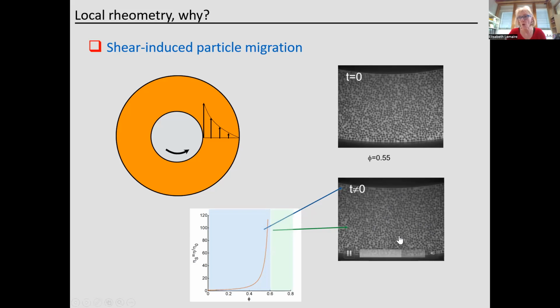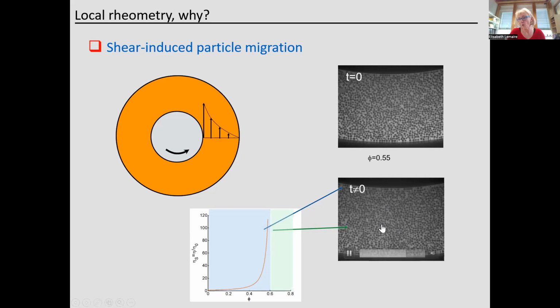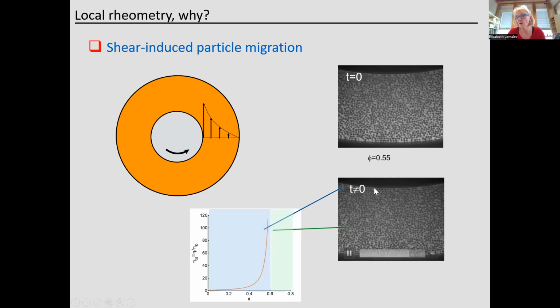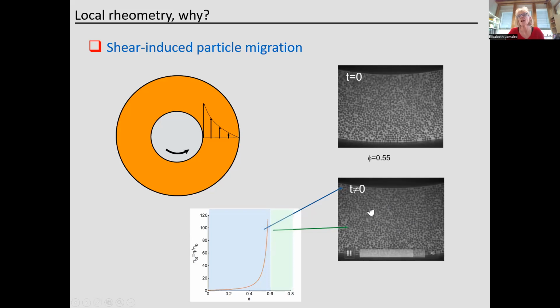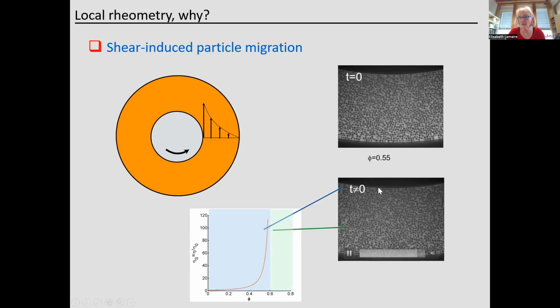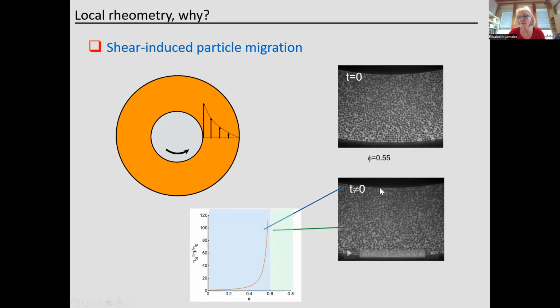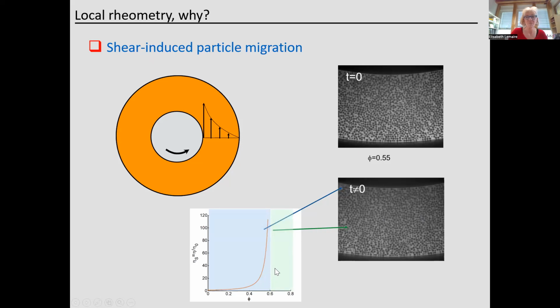There is no flow. And why is there no flow? There is no flow because there has been a particle migration from the inner cylinder toward the outer cylinder. And so in this region, the particle volume fraction is higher than the jamming fraction. Okay, so here the suspension cannot flow.